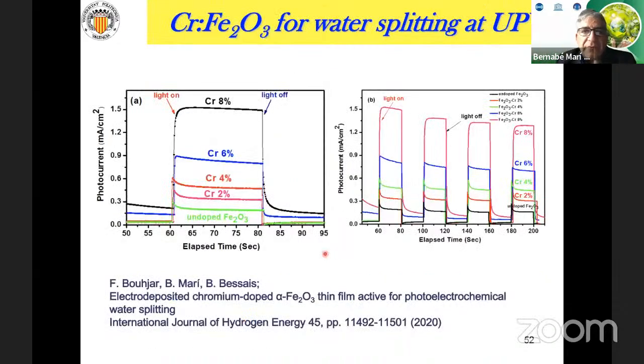In our lab, we have also worked on that. So in our lab, we have produced hematite, chromium-doped hematite for water splitting. Here you have some of the results. This slide represents the photocurrent as a function of time. So if we increase the doping with chromium, the photocurrent increases considerably.